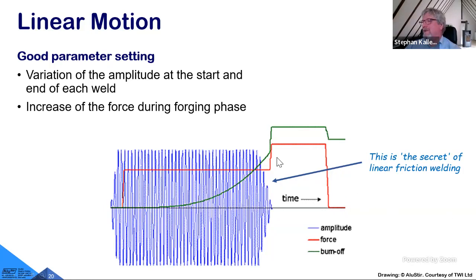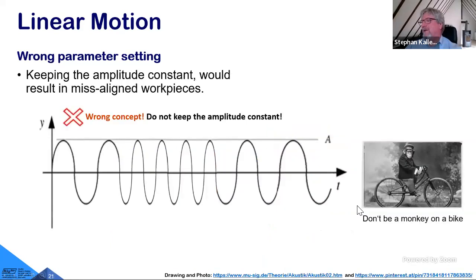And here you see that the force in this case, the red curve, has been significantly increased at the end when the parts are stationary, have been slowed, and the amplitude has been ramped down. And then most of the flash is being generated in that phase at the very end, in which we increase the forging force at the end of the weld.